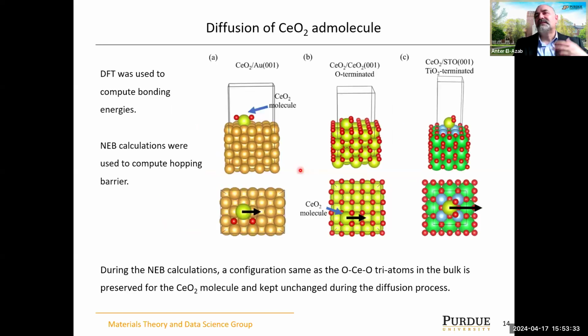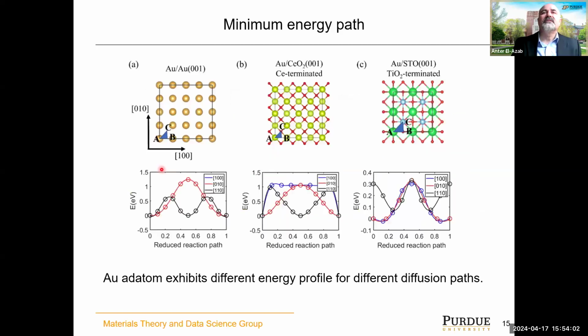So we did these simulations by DFT to calculate the energetics. The bonding energy is just the bonding energy; you compute it from the structure. For the hopping energy, you have to use the so-called nudged elastic band calculations. It's a scheme that looks at transitions between states, and you capture the energy difference between the initial and the so-called transition state when the system is jumping from one state to the other.